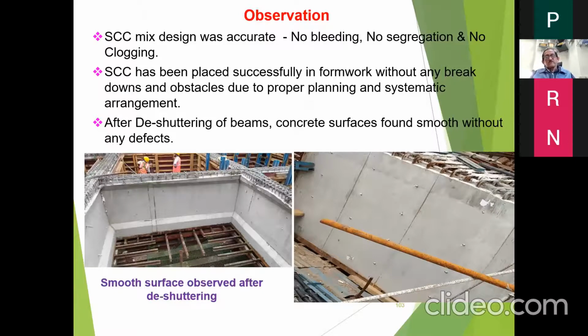After the formwork is removed, you can see the smooth surface after deshuttering, and these surfaces are still visible today, where they are now painted but not plastered. So it is form finish concrete, and you can see the finish, although the depth of the main beam here is 2.8 meters, and this is 1.5 meters. You can see the finishes and the haunch portion, etc. Normally the honeycombing would come near the haunch portion where there are negative slopes, a negative change in direction of the shutter. After deshuttering, the concrete surface was found smooth without any defects.